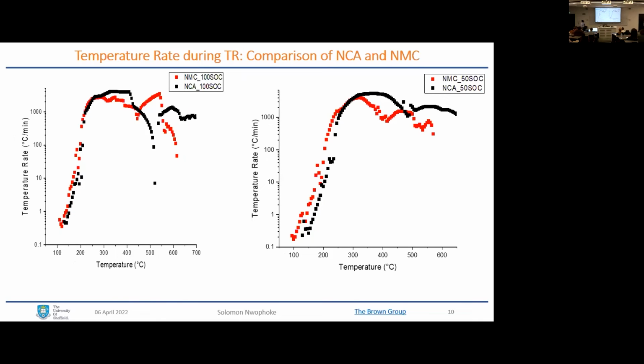Then comparing the heating rate of those two samples at 100 state of charge, you see the NMC here has a similar heating rate, but it just occurred a little bit earlier than the NCA. And the same happened at 50 state of charge as well. But what this indicates is that for NMC, the reaction occurred more rapidly, and the maximum heating rate was attained earlier, and then it sluggishly reduces the heating rate from the maximum point, then cools.